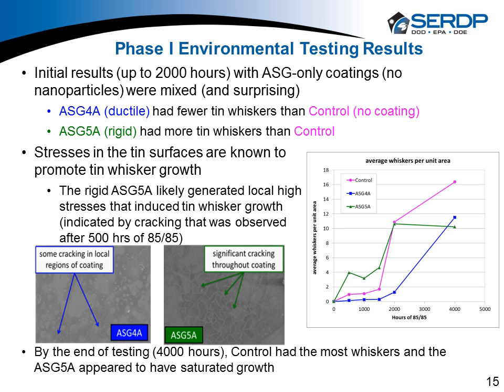Yeah, very good question. What we looked at is while ASG4 didn't crack nearly as readily as ASG5, it started to crack later on. As the coating develops those stress cracks, which you can see real well here in ASG5, that allowed the environment, the moisture and high temp, high humidity, to get down to that surface. So we end up with the same type of whiskers. It just was a delay compared to ASG5. And what that told us is we need to make sure our formulation is more towards the less stress type of coating than the right side.